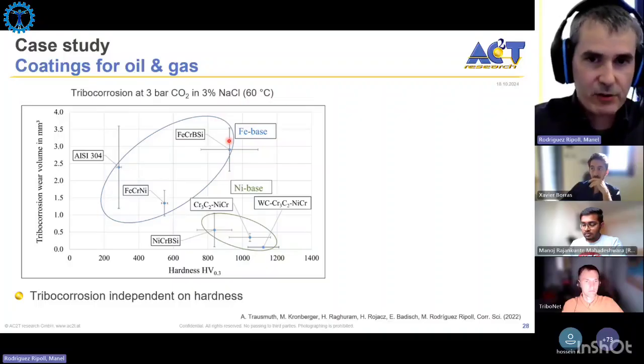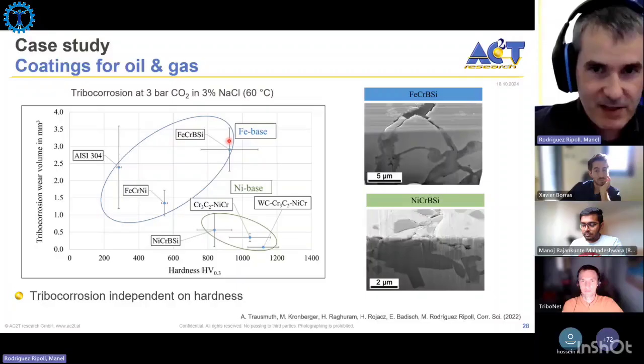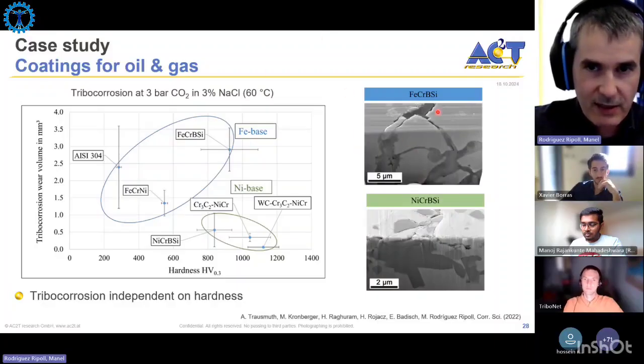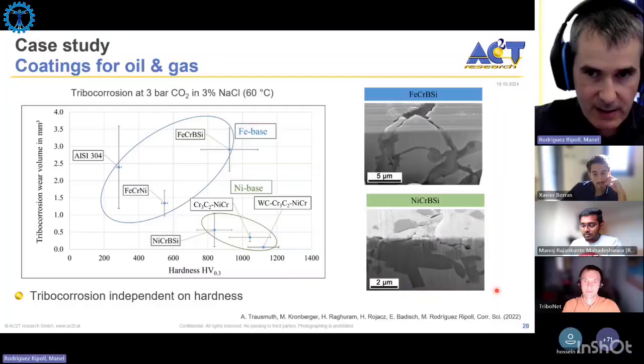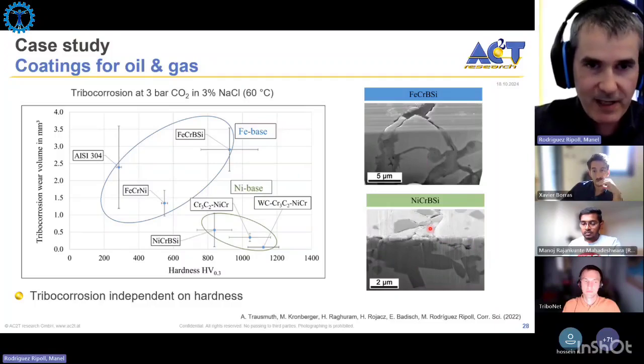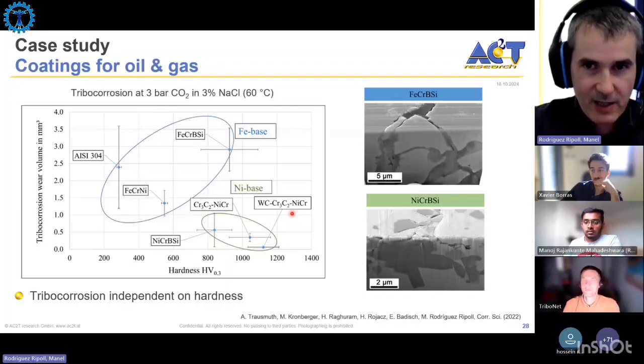And the reason for this is something I didn't touch today too much, but it's very important also in tribocorrosion, is to check the microstructure after the experiments. And you can see here, this is a cross-section. This is the sliding surface. You can see some sliding grooves. And what you can see here is this iron chrome boron silicon plasma spray coating is prone to selective corrosion along the grain boundaries. That is responsible for having this poor tribocorrosion wear performance, whereas this nickel chrome boron silicon, you can see that in the wear scar you hardly see any scratch or any groove, and in the cross section you can see maybe some superficial cracks, very small ones, but very little damage. And that's the reason why these two materials, despite having exactly or very similar initial hardness, one of them is much more prone to tribocorrosive wear when compared to the other one.